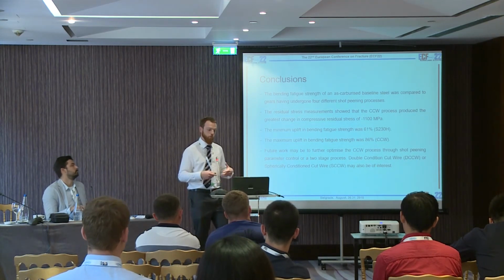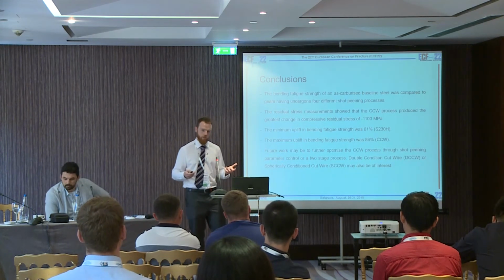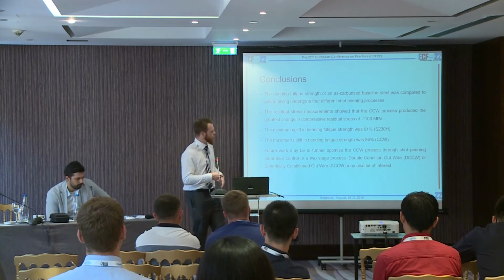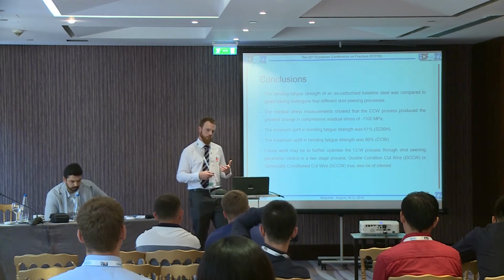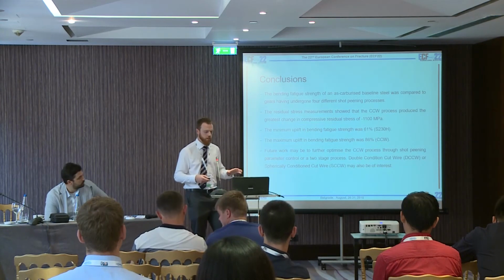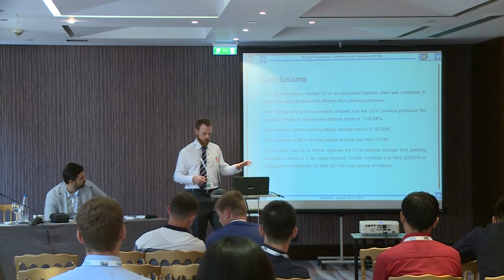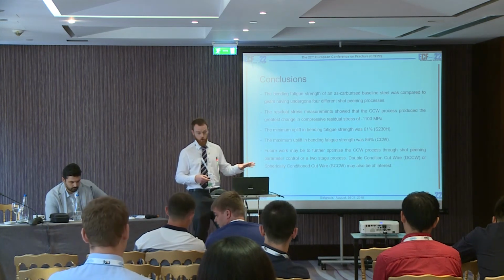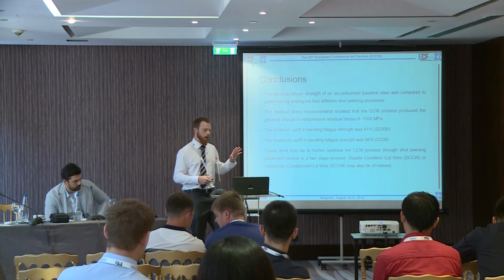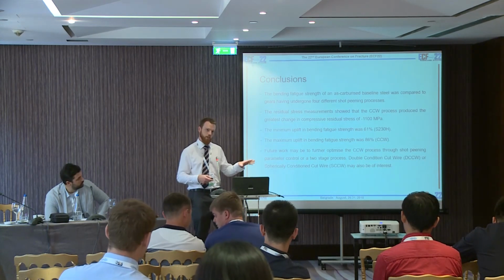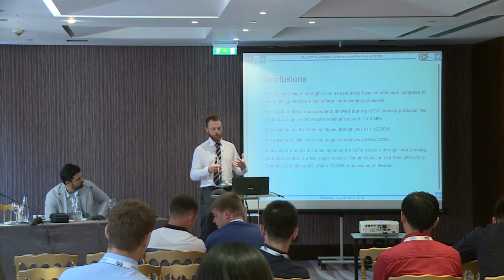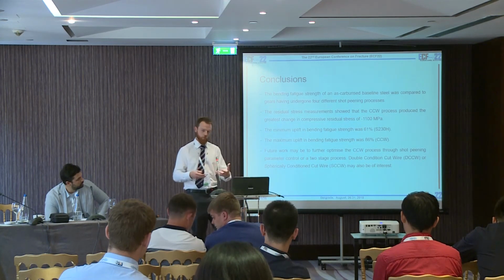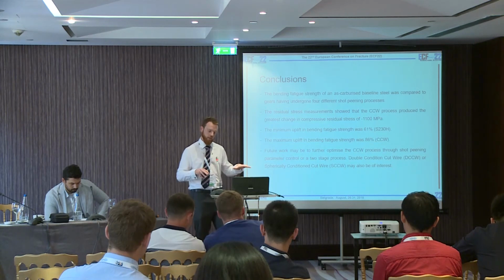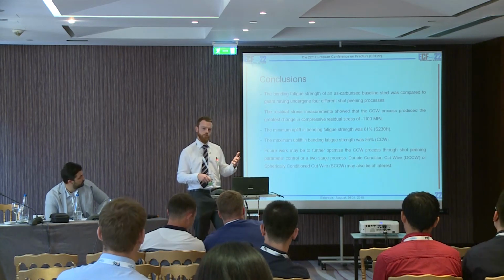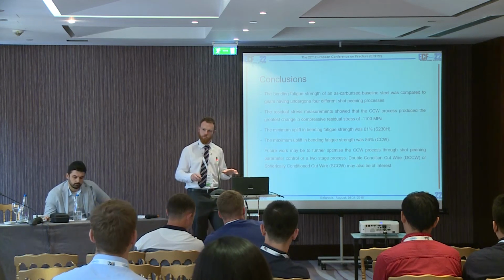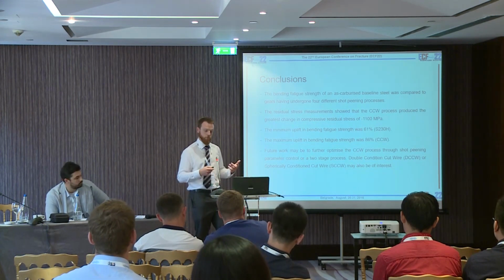Future work, we would suggest we'd be looking at additional optimization of condition cut wire processes. Again, in this package of work, we didn't look at surface roughness, so there may well be some surface roughness effects. However, previous work, and I can find paper references if people are interested, did look at surface roughness and bending fatigue failures. However, they were comparing them across different media processes. So again, perhaps there's maybe something to look at with the same condition cut wire shot peening process, and then trying to establish a secondary process, maybe a duplex process, to change the surface roughness parameters, which isolates some of those different effects from the other shot peening processes.